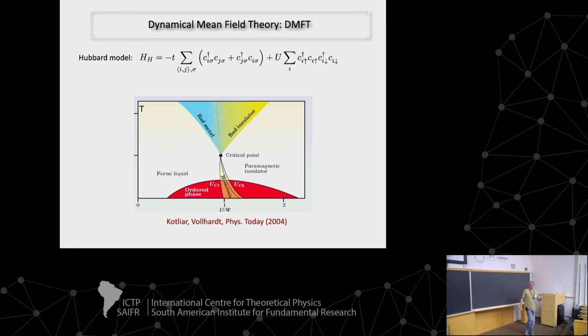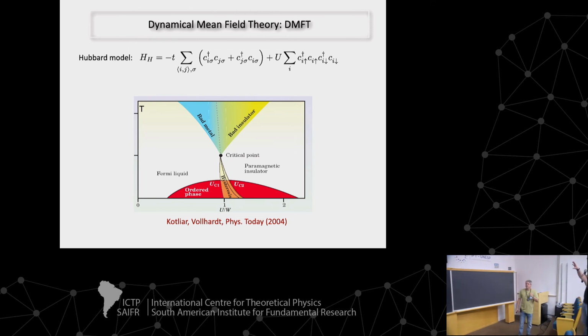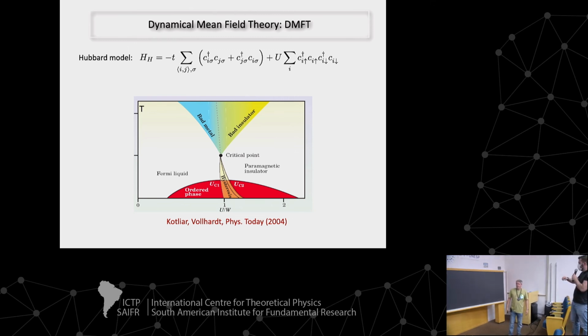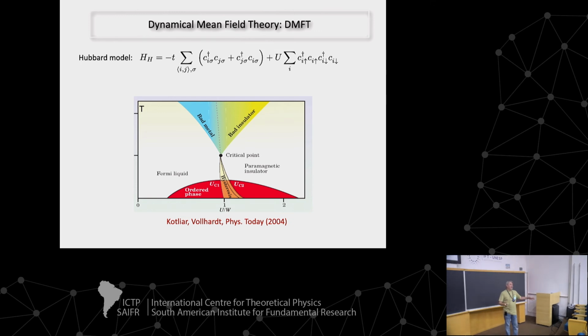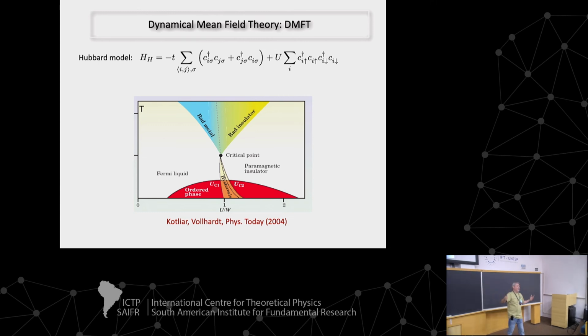The other question is, how many sites do you use in your calculation? So you do really brute force, in the statistical one, you do brute force. Brute force, finite lattice, yes. On each site you solve the DMFT. Yes, so a nightmare, complete nightmare. I know. Now, for the other case, we found the bulk solution for the metal, the bulk solution for the insulator, and the unstable point of the Landau functional. This is in the thermodynamic limit, it doesn't have sizes.